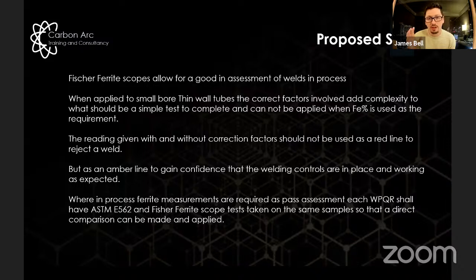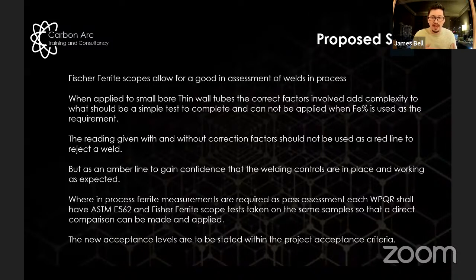What we ended up agreeing as the close out with this last point was that for every procedure qualification we do, from the same location, we will take ASTM E562 point count data and Fischer Feritscope test it, and produce a tolerance on the Fischer Feritscope reading. We got to a point where we agreed that the Fischer Feritscope reading could be down to 25% and still be okay. Once it got below that, we'd need to do extra tests to make sure it was okay.